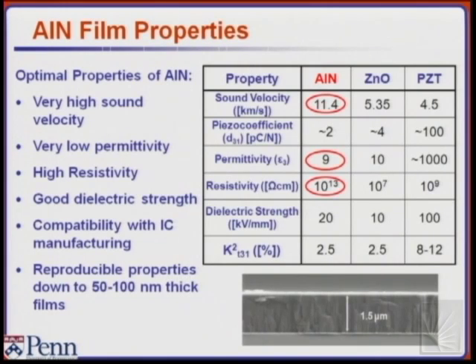We have a very good dielectric strength and a decent electromechanical coupling, which is basically how effectively we convert mechanical into electrical energy. PZT would be the best material to pick at that point, but the advantages you get by going to PZT don't scale very well with size. We were able, and I'll show you some results at a 100 nanometer scale, to maintain the same properties that we get at 1 or 2 micron thicknesses, which are the material properties used to generate this table. If I generate the same table for PZT at 200 nanometers, this factor becomes 10 times lower, based on experimental results. Theoretically, yes, you can get there, but people have effectively seen a degradation of PZT at those scales. So it might be a real challenge.